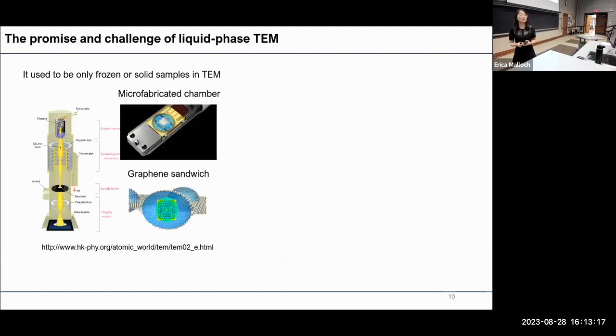So here comes my group's unique contribution to the field. We introduced liquid phase TEM to capture the complete crystallization process of a colloidal nanoparticle suspension. We have two ways to do liquid phase TEM. One is to use this microfabricated chamber to make sure we can sandwich and seal a liquid sample. At the same time, we can also do in situ stimulation. We can change the solvent, change the temperature, and also apply electrical bias. We can also do a graphene liquid cell, shown here, which has wonderful contrast and minimizes electron beam effect.